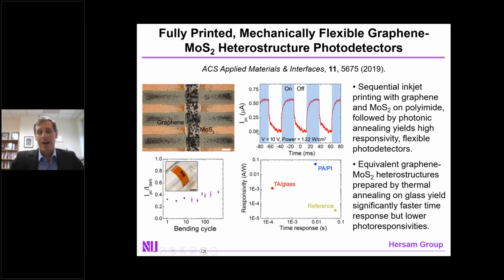I note that the contacts to these devices are also created using printing. In this case, printable graphene is used as the contacts. And what we can see is that the performance in terms of responsivity depends upon not only the quality of the material, but also the way in which you do the curing. And that if you do thermal annealing, which is a relatively slow volatilization of the ethyl cellulose polymer, that gives you a very well-ordered morphology, which gives you fast time response, but relatively low responsivity.